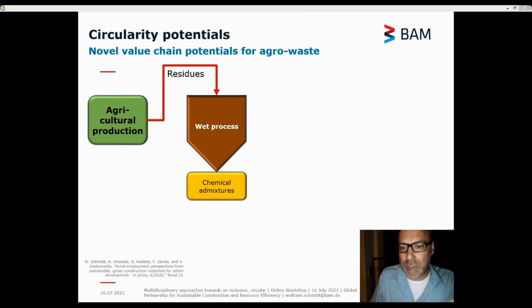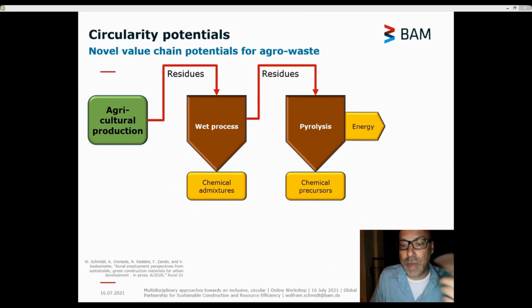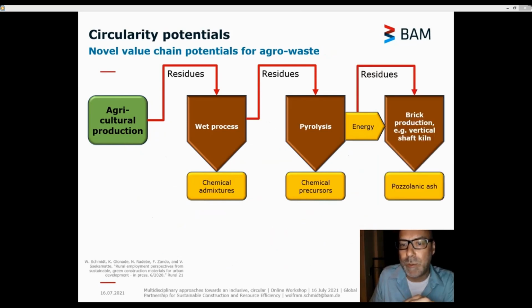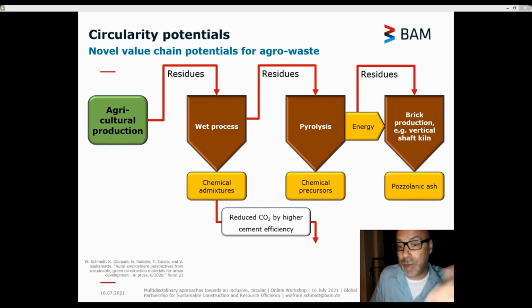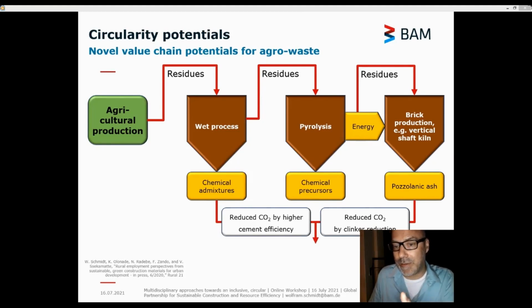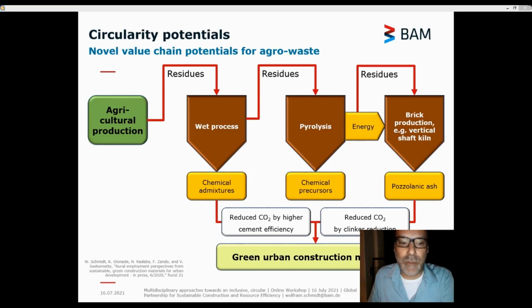And just to show you quickly how that works, if we take the agricultural wastes, the residues will get into a wet process where we can obtain chemical admixtures. The residues of that process get into a pyrolysis where we can obtain chemical precursors, which can go into the asphalt industry, for example, or sealants. And the energy that is produced from here, carbon-free at the moment, can be used to fire a brick process. And the residues, the biochar from the pyrolysis, can be added to the brick production as an internal fuel. And then from the kiln you do not only obtain the bricks, but you also obtain a pozzolanic ash. And with the chemical admixtures that help reduce the water content, and with the pozzolanic ash that helps reduce the Portland cement clinker content in concrete, we can really create green urban construction materials.